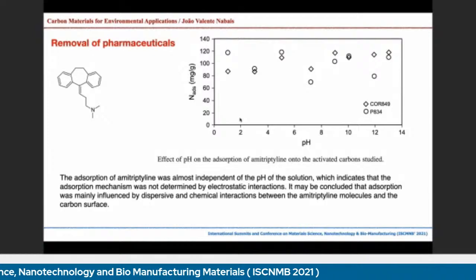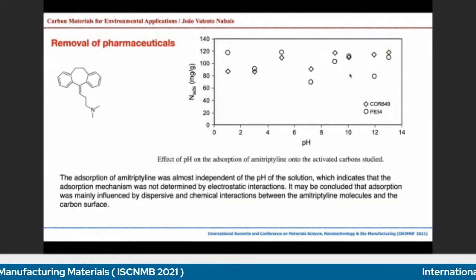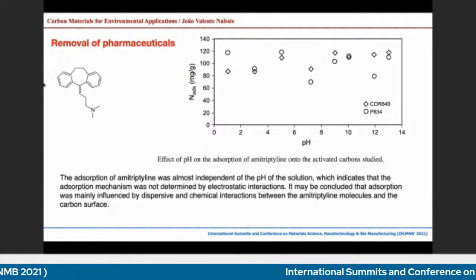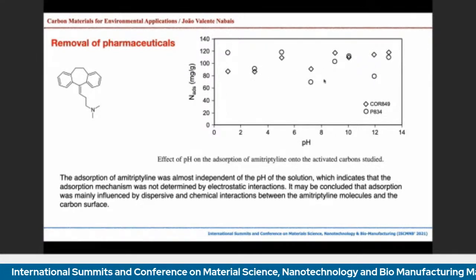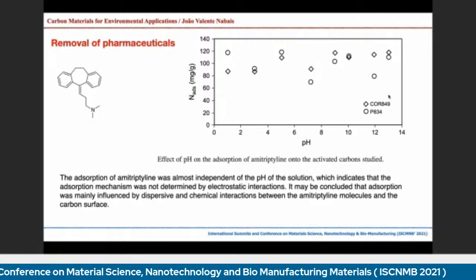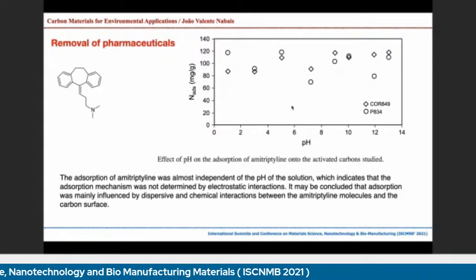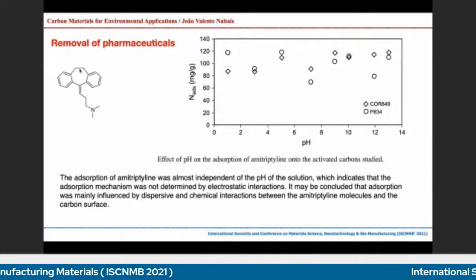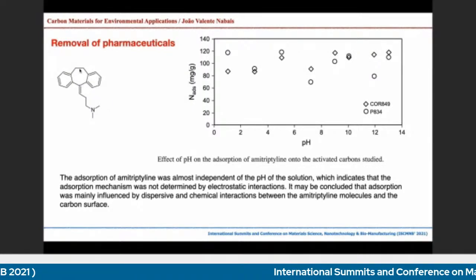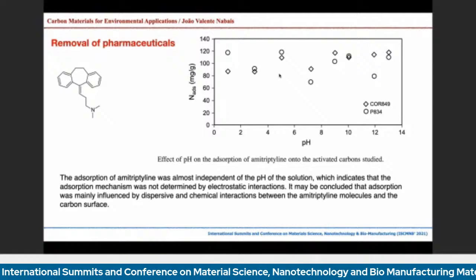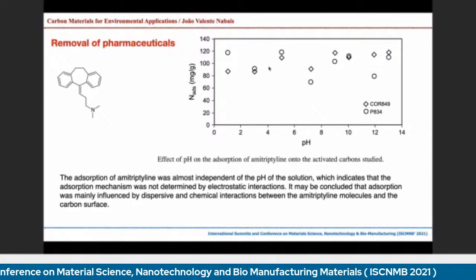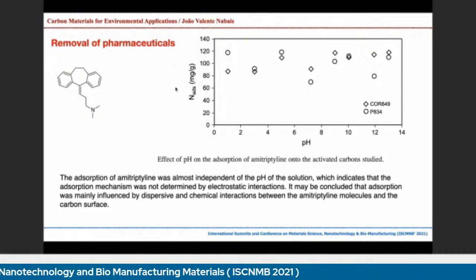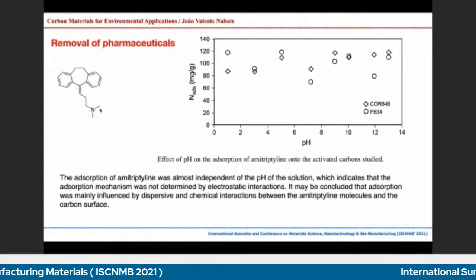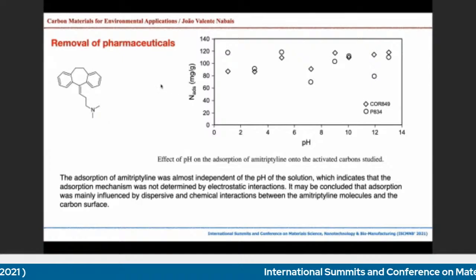which was quite interesting for us when we studied the influence of the pH in the adsorption of this pharmaceutical. You can see that there was no major change in the adsorption with pH, which means that the adsorption was not determined by electrostatic interactions, meaning that electrostatic interaction was not the driving force for adsorption. So it might be linked also with specific chemical interactions with this specific nitrogen group, with the functional groups of the surface of the carbons.